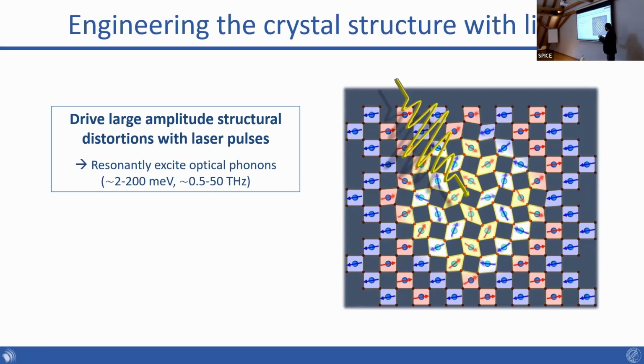Okay, and so the advantage of this is that you have the ability to really specifically target the atomic motions that you're interested in. The price you have to pay is that you have to now work in this frequency range, which is somewhat difficult to access. So in Hamburg, we spent a lot of time to develop optical sources that can access this frequency range. And now we have the ability to essentially pump the entire frequency range with intense pulses on the order of a few megavolts per centimeter. We don't use a free electron laser, we use tabletop sources, but we can still get to reasonably large electric field intensities at your sample position.